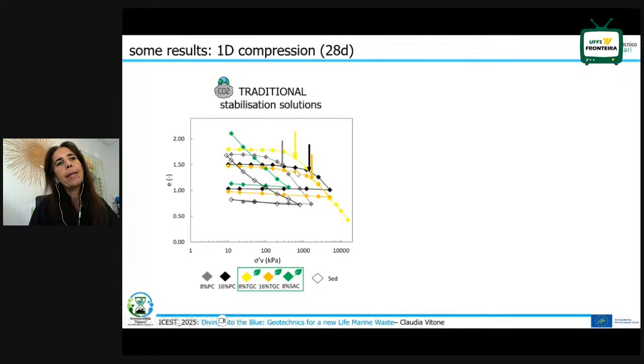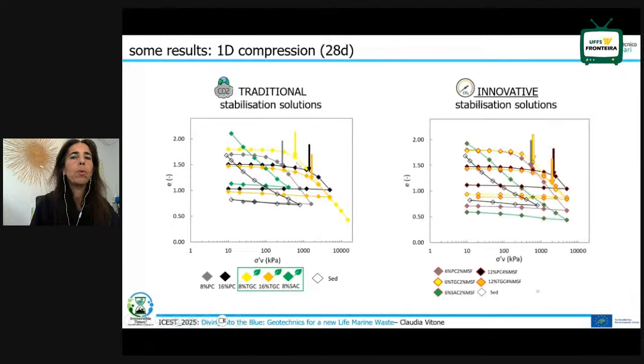You can see here, first of all, that the treatment is working well because we have, differently from the natural sediment, a pre-yielding behavior, then we have the yielding, and then we have the normal compression behavior. Here, this is the virgin compression line. So we have a yielding due to the chemical reactions. But this is not the case for the sulfoaluminate, which was essentially not working. But both the Portland and the steel slag were working very well.